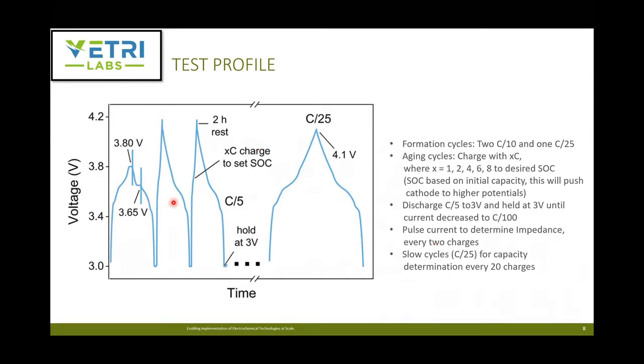As part of these cycles, every 2 charge cycles, to determine the impedance, they did a high pulse like this to determine the impedance, and then a slow charge cycle every 20 charges to determine what is the capacity that's left in the total cell. That's the C over 25 up to 4.1 volts.